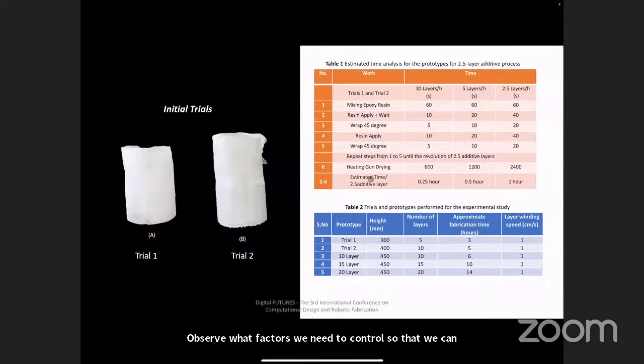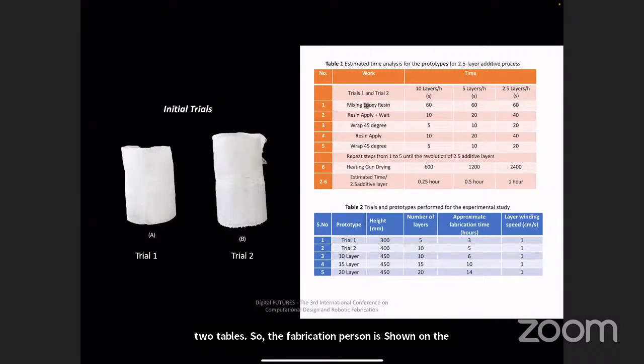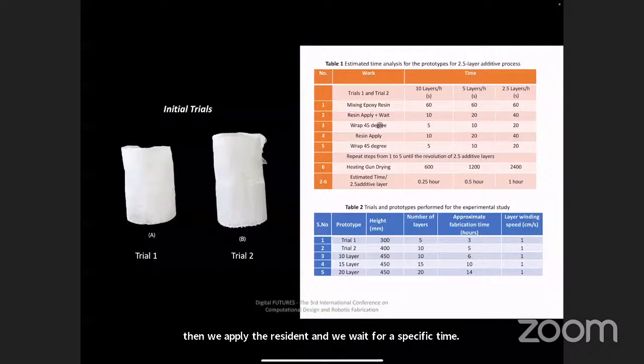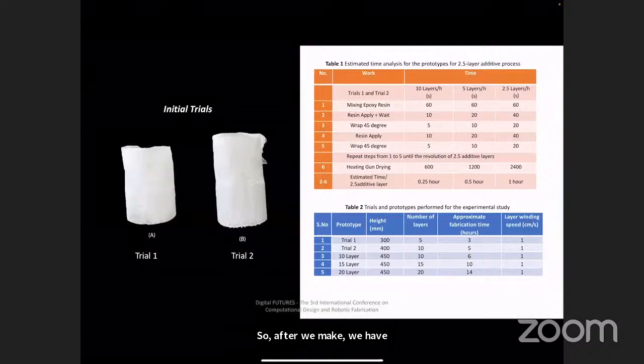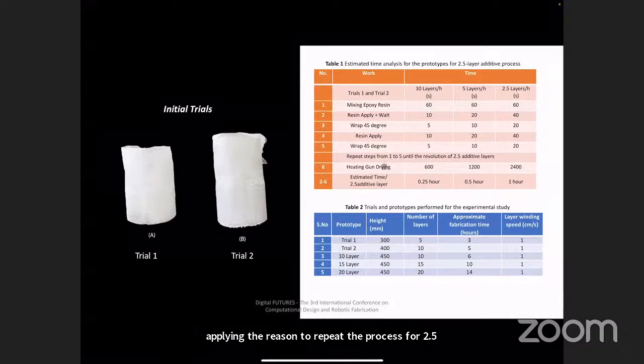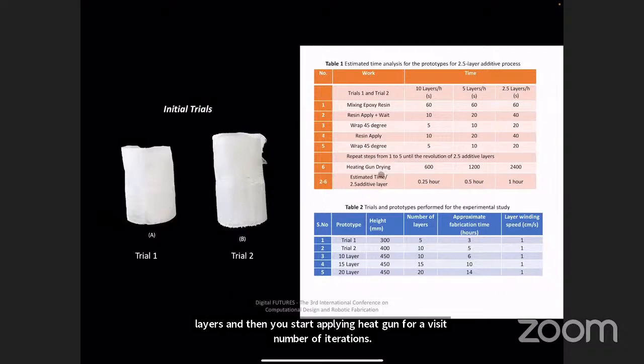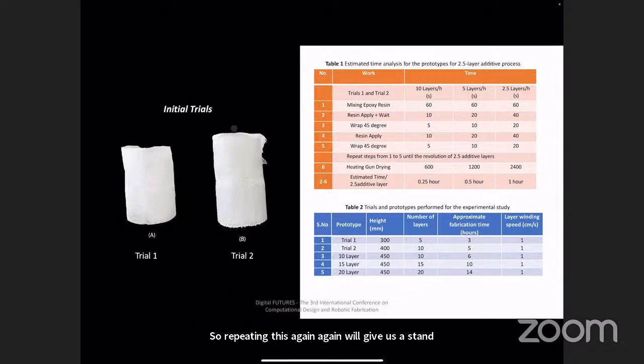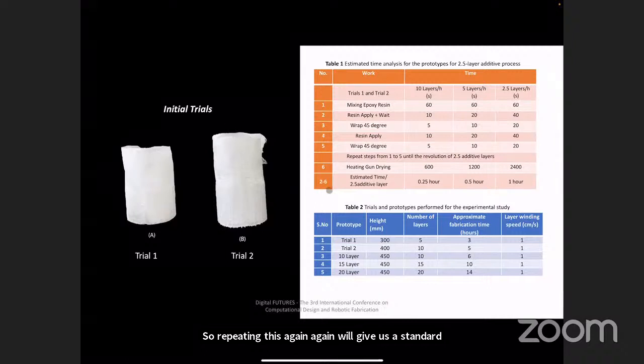On the right, there are two tables. The fabrication procedure is shown in table 1. First, we mix the epoxy resin, and based on the number of layers, whether it's 10, 5, or 2.5 layers per hour as programmed in the Rhino or Grasshopper environment, we apply the resin and wait for a specific time. After we wait, we rotate the robot by 45 degrees and again start applying the resin. We repeat the process for 2.5 layers, and then we apply the heat gun for a fixed duration. Repeating this again and again will give us the standard length and height of the geometry.